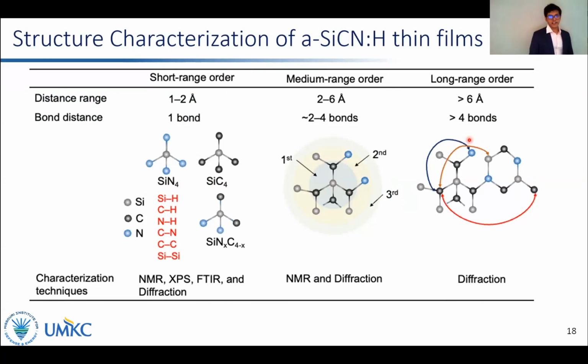Structure characterization for disordered materials can be done at different length scales, including short range order, medium range order, and long range order. Short range order is confined to the local structure, probably a single bond distance of 1 to 2 angstroms. Possible local structures for the proposed materials include SiN4 or SiC4, or mixed environments where silicon is bonded to both carbon and nitrogen. A variety of hydrogenated bonds or homonuclear bonds could also be present in these materials.